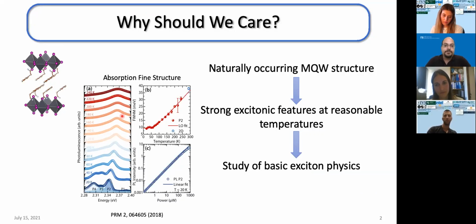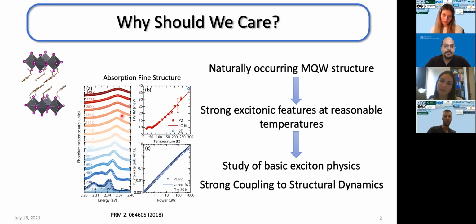which we would normally have to go to very, very low temperatures in order to see. Moreover, the two-dimensional perovskites exhibit strong coupling between excitonic and electronic properties and their structural dynamics, mainly their vibrations inside the material, which again, you can see here in the temperature-dependent absorption. So for starters, at low temperature, we can see what is called the absorption fine structure due to coupling to vibrations. And as we increase temperature, we populate more and more vibrations in the material, and the electronic properties change, exactly due to this coupling.